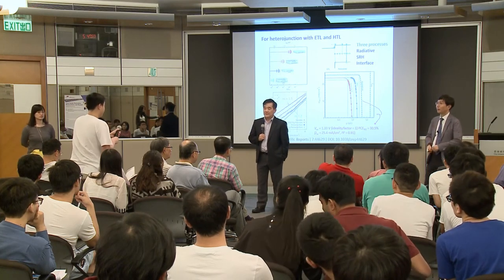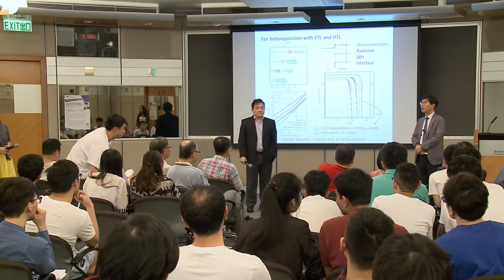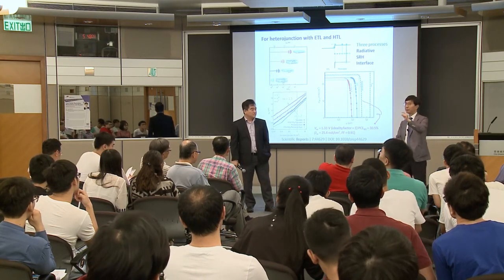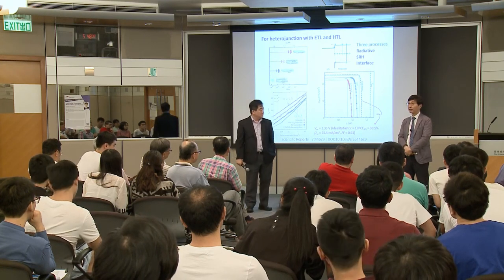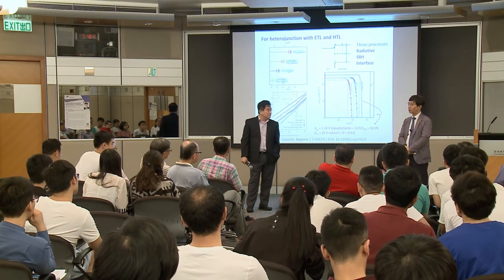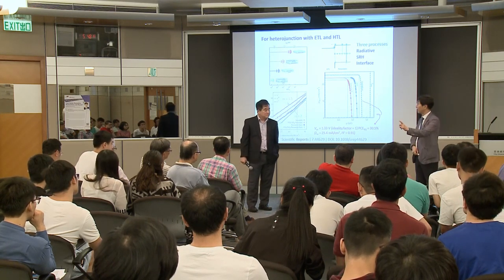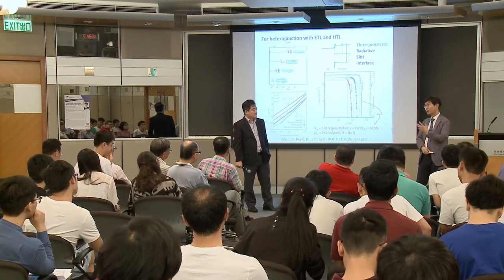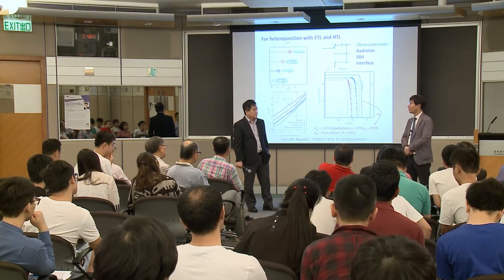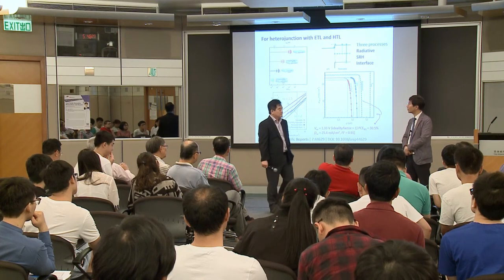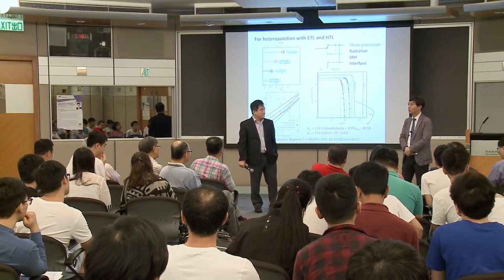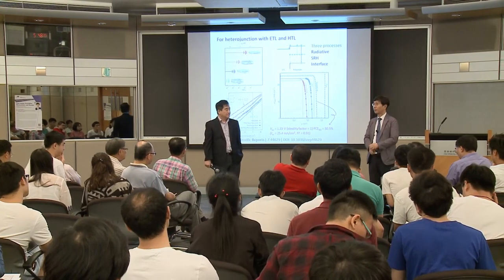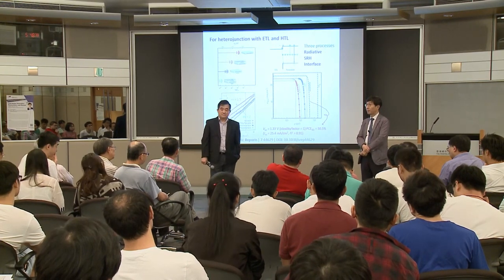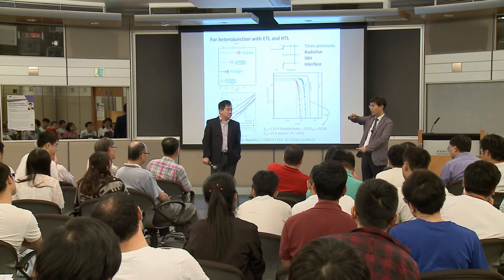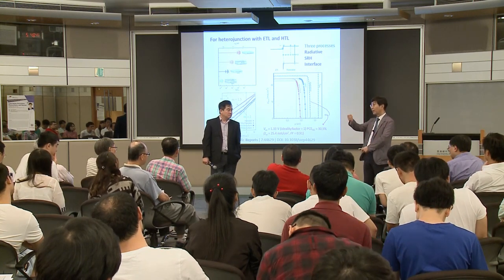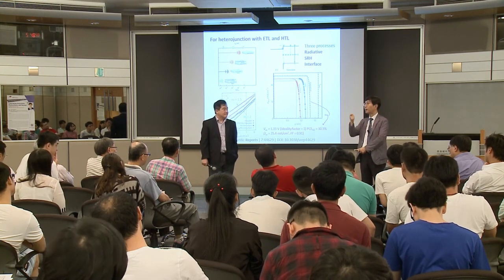Oh, that's a very good question. Initially, with solution-cast perovskite films, people started to understand the electron-hole mobility and electron-hole diffusion length, and at that time it was very short, around 100 nanometers. And then from the single crystal, I could not remember exactly, it's 100 micrometers or more, a much longer diffusion length. So if we have a long diffusion length, then we can apply this material to an X-ray imaging system. Because upon the X-ray beam, charge is generated and collected at the back plane, and in that case the diffusion length is very important.